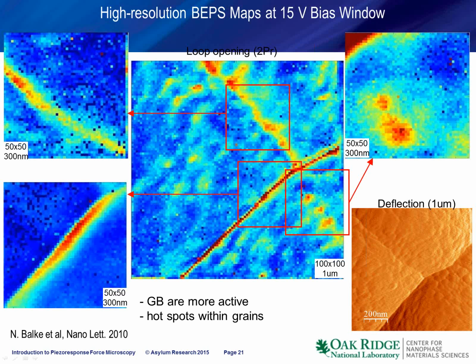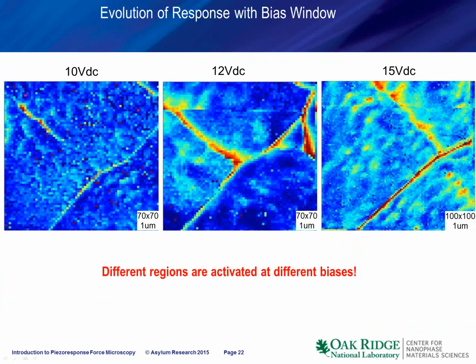And we also know that this is not crosstalk, because crosstalk changes the absolute strength of the signal, but generally does not result in the hysteresis loop opening. So this measurement of the electrochemical strain gives us insight into the electrochemical activity on the tens of nanometers length scales. In fact, we can go beyond that, and we can study the more complex behavior of the materials.